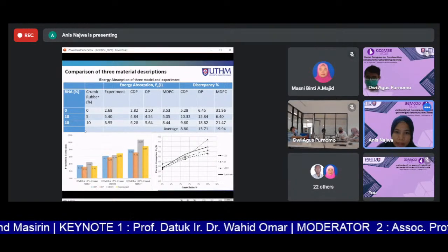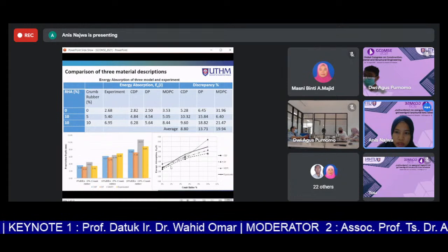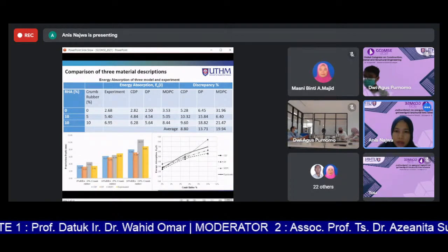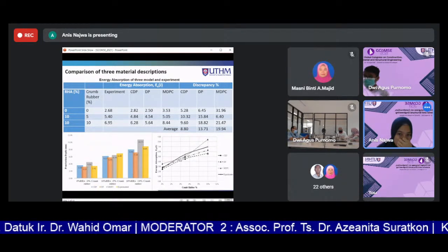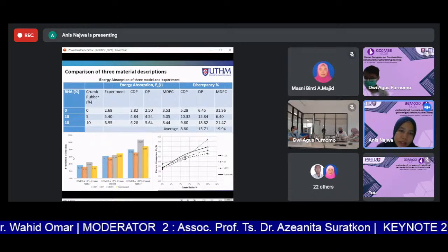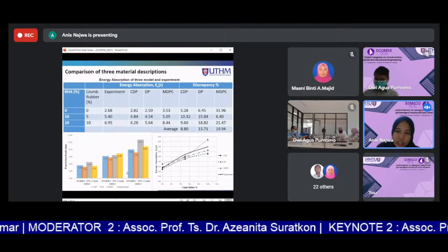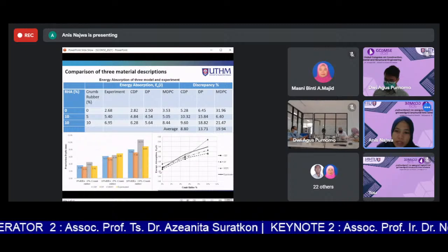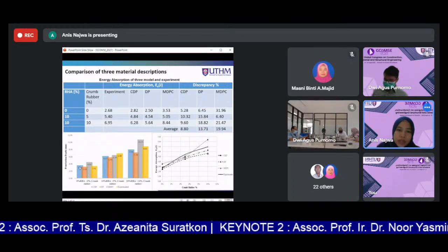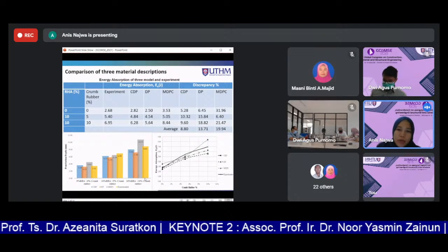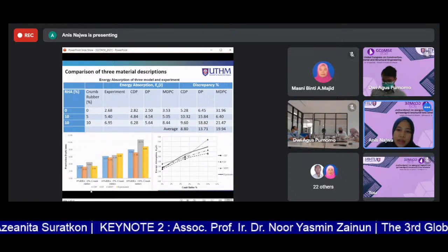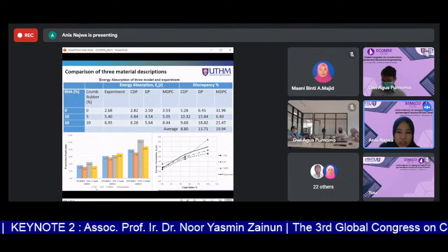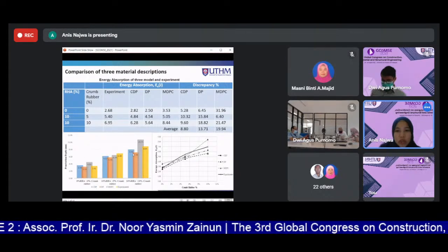So to be clear, here are the figures, the line graph and also the bar graph. They show the penetration depth versus the percentage and also the energy absorption versus the crumb rubber. It shows that compared with the experimental results, CDP, DP, and also MDPC, CDP concrete damage plasticity is the closest to the experimental here.